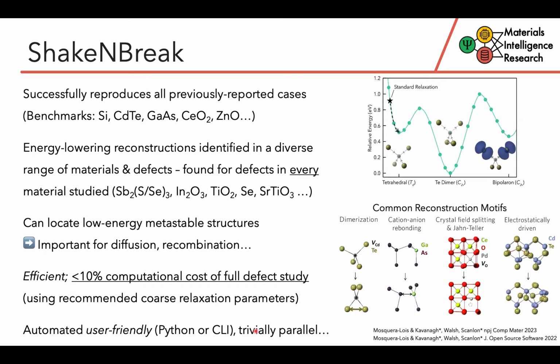So in summary, the strategy with ShakeNBreak is to try and use this coarse exploration of the potential energy surface to identify potential locally stable defect structures before continuing with the final converged energy calculations. We found the method to be extremely and surprisingly successful, particularly given some of its simplicity at the core. And then by applying it to a wide and diverse range of materials, we've seen that this is quite a widespread behavior for defect solids, and we've seen it occur for defects in every material that we've looked at so far.